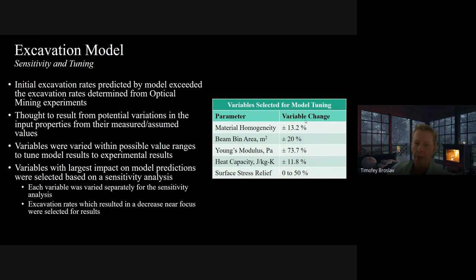So initial excavation rates predicted by the model actually exceeded the rates determined from the experiments. And so this was thought to result from potential variations in the input properties due to errors in either their measured or their assumed values. Now, it was assumed that these variables varied within certain ranges, and so they were varied within the model to see how they affected the results. Now, variables with the largest impact on the model predictions were selected based on sensitivity analysis. We couldn't really vary every single variable. That was too time consuming. And excavation rates, which resulted in a decrease near focus from the sensitivity and tuning effort, were selected for showcasing the results in the model.